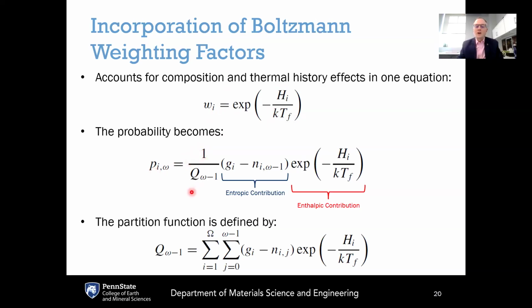It's going to be 1 over the partition function. The partition function is just shown at the bottom here. That's just a normalization factor for the probabilities. And then times the entropic contribution. This entropic contribution is just the number of atoms that are still available. So this would be the total degeneracy of those atoms, G sub I.